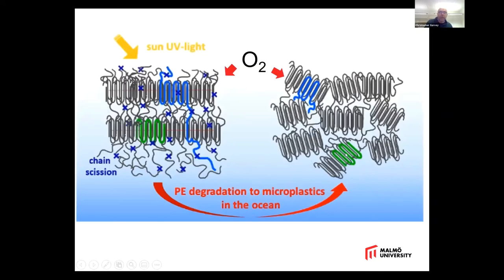So this is a summary of the process: the chains are cut, and this barrier, this lamellar structure, is disrupted. And this is the important issue, I think, in terms of the long-term lifetime of this material: it's much easier for oxygen to diffuse into this material. The next stage of this work is to actually look at how this affects the oxidation.